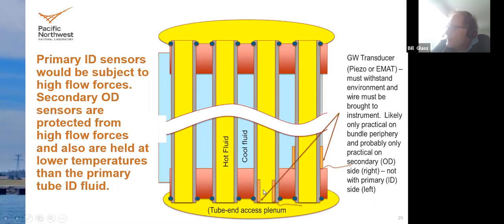Online, when the heat exchanger is operating, this is a high flow area. You've got a great deal of difficulty trying to get the wire out of this plenum, plus it would occlude the fluid and render that tube way less efficient, which is undesirable from the overall operation of the plant. If, however, by contrast, you put the sensor on the outside of the tube, here, then it's in a relatively stagnant flow zone, and you can monitor the tube condition from the outside, or the tube OD.